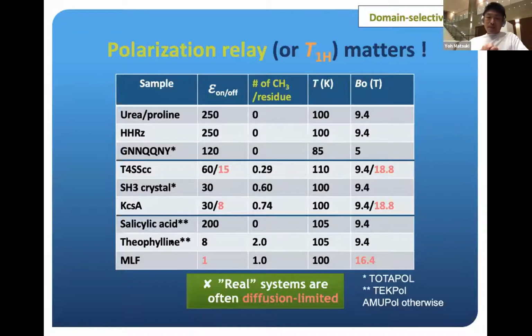So this has made us more and more interested in the inhomogeneous distribution of hyperpolarization in the sample system, which should be a function of the relay efficiency of the polarization in the system, which is dictated in turn by the local T1 for proton. Because proton T1 is most significantly affected by the methyl group rotation at low temperature. So I dug into the literature, found this interesting correlation between the reported enhancement factor and the number of methyl groups or methyl group density in each sample system.